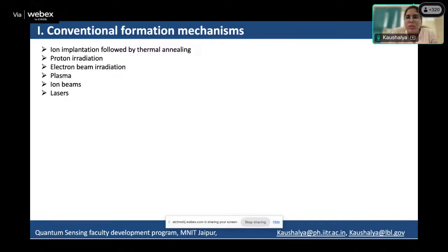One could also use other types of irradiation, for example, proton irradiation. If you just shine energetic protons onto your silicon, it can already make some of these defects. If, let's say, some carbon and hydrogen is already present in the silicon lattice from storage, because these are just hydrocarbons, they can diffuse into your materials as well. So you can simply do proton irradiation, move these atoms around a little bit, and that can easily make these color centers.